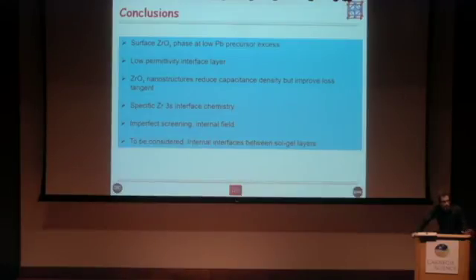We've seen this, it's reproducible first of all, so it's a real result. But it may be to do with the exact temperatures we've used for the crystallization. We do two rapid thermal annealings, one after the first layer, which is the seed layer, the PZT, and one after the rest. And as you know, because of the crystallization temperatures, there's a strong gradient between the titanium and the zirconium in each layer. So what goes down first is titanium-rich. At the bottom of your layer, you will have PTO, or almost PTO. So in fact, what we're looking at in that seed layer is the growth of PTO on platinum, rather than PZT. So this may have something to do with it. We can talk later. Yeah. Thank you. Come on up.